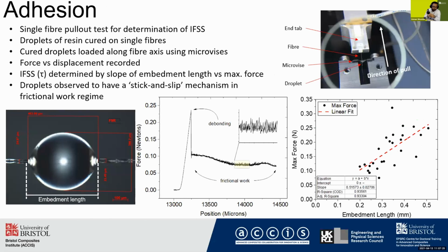To understand the effects of plasma treatment on adhesion, we did single fiber testing, predominantly microbond testing, where a droplet of epoxy resin was cured onto the surface of a single fiber and then pulled through a set of microvices to find the total force that is required to debond the droplet from the fiber. So once we have the maximum force for each sample, we would plot it against embedment length to determine the interfacial shear strength.